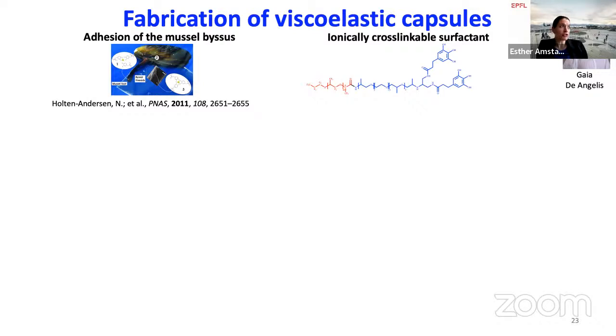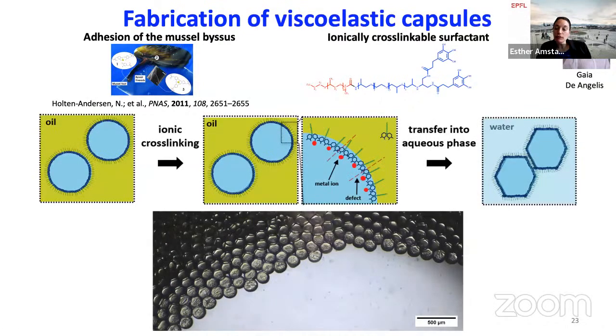And if you think about the structure, you wouldn't expect these kind of surfactants to form well-defined layers, because they have only one ionically cross-linkable group per molecule. And to get percolating networks, you need at least two, actually better three. But just for chemistry reasons, three is even more complicated than two. So we made a second generation of surfactant that has two such catechol derivatives per molecule. And we ionically cross-linked them, and we could immediately see that these shells are a lot more stable. And actually now we can tune permeability of these capsules quite well by changing pH and the type of ions.